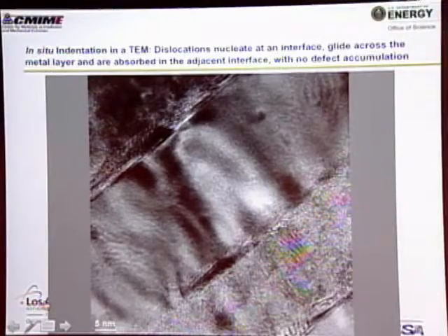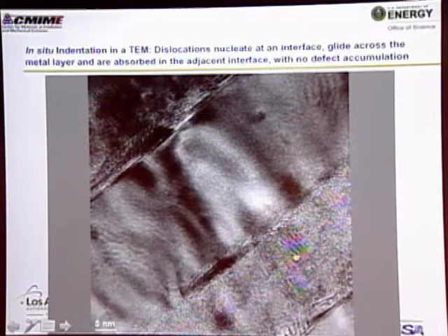So again, you don't have to take my word for it. Seeing is believing. This is a copper niobium multilayer. The center here is copper. This is niobium here. This is niobium here. This is work that Nan Lee does, who's also here in the room. Nan, where are you? He's right over here. So this is work that he does in the electron microscope and deforms this material and watches exactly what happens to the dislocations as they move through the material. So what you're going to see here is that the interfaces are going to emit different types of defects.